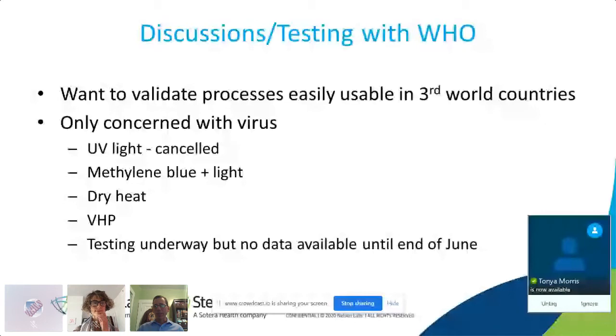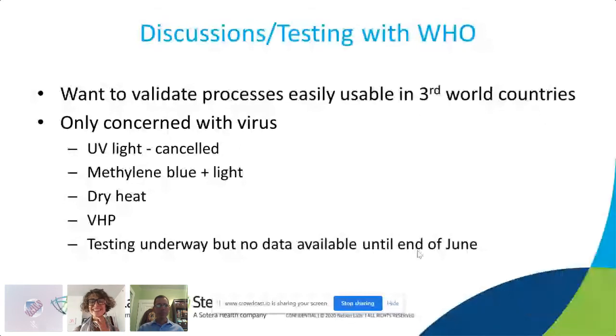Sorry about that. I forgot to disable my IM system. I'd used methylene blue before, but I did not realize that methylene blue in the presence of light actually has a fairly well understood bactericidal activity. So it's really simple. You just spray the methylene blue on the mask material and expose it to light, even sunlight, and then it has a fairly decent log reduction. Now their focus was only on viruses. That was their primary concern in gathering this initial set of data for WHO.